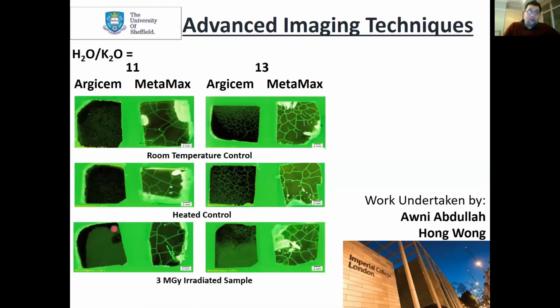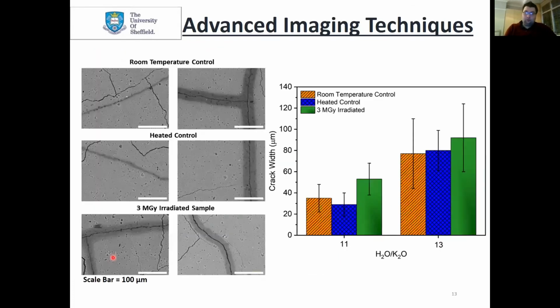This work was done at Imperial College, using a fluorescent epoxy impregnated into the sample. You've got room temperature, heated, and irradiated samples here at the bottom. The Argicem material fundamentally has more epoxy impregnated into it. I'm not going to go on any more about the porosity here.